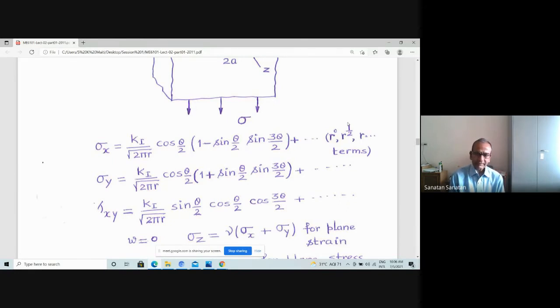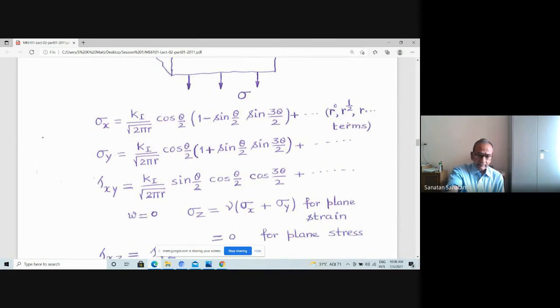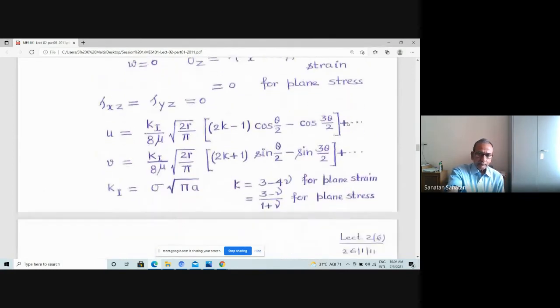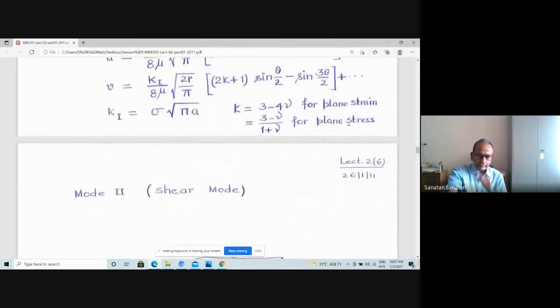Stress actually becomes infinity at R equal to 0, and the R theta function is there. In fact, it is the first term of the infinite expansion. First term is R to the power minus half. Next term is R to the power 0, then R to the power plus half. This common difference in the exponent is half. So this is the form of the stress field. So this is how it is.